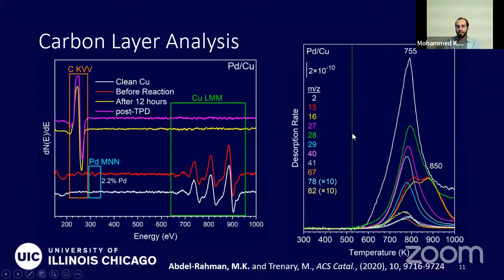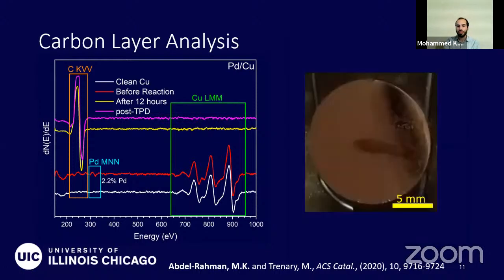And this green dotted line in the TPD spectrum is the temperature at which the palladium atoms will dissolve into the bulk of the crystal. And so we lose our single atom alloy surface at that point. So all of our reactions were carried out in this range, 300 to 400. So the surface is still pretty much a single atom alloy. And of course, taking a picture afterwards, we see that there is a black spot here in the center of the sample. And that's where the carbonaceous surface interacted with the electron beam from the Auger source.